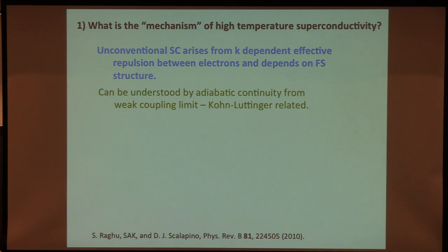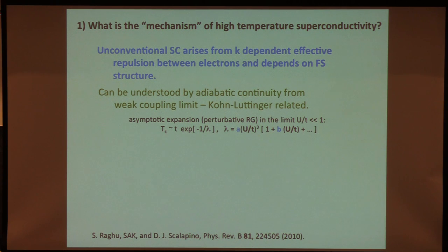But what we did was we asked, could we understand this thing in a theoretically responsible way in any limit? And the limit it can be understood is in the limit of weak repulsion. Say, take the Hubbard model with a very small value of the repulsion U, and then we can write down an asymptotically exact expression for Tc, which is some cutoff times e to the minus 1 over lambda, and one can calculate the first two terms in the asymptotic expansion for lambda. These coefficients a and b depend only on the band structure. They're features of the non-interacting system, and this can be derived using renormalization group as an asymptotic expression.